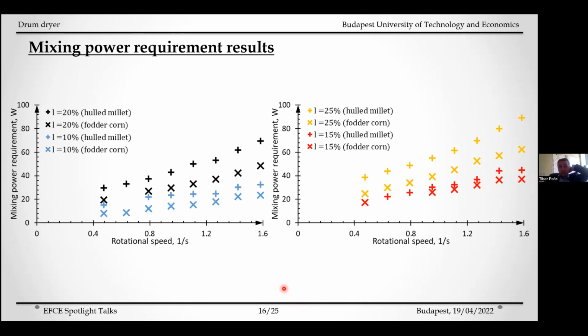Some results of the laboratory measurements are shown in these figures, where the real mixing power is depicted as a function of the rotational speed for various drum loading factors. Based on the results, it can be established that the mixing power requirement increased as the loading factor of the drum was increased, because the mixing elements move more material.